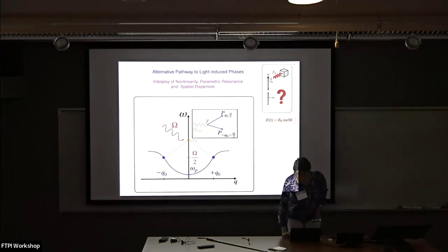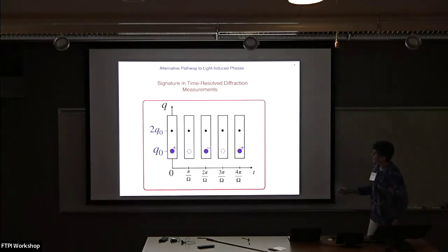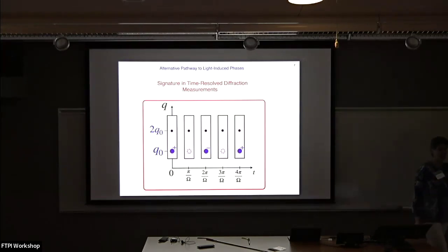So in keeping with the spirit of this conference, I should say that there will be a signature in time resolved diffraction measurements. And in fact, what I expect is that at Q0, the modulation that's tuned by the drive frequency over 2, I will get a spatiotemporal mode that will be intense. It will show up as a frequency of omega over 2, so it has a period of 4 pi over omega. And there will be a much less intense static mode at 2Q0. And these are both modes that are very different from what's going on in the current equilibrium.